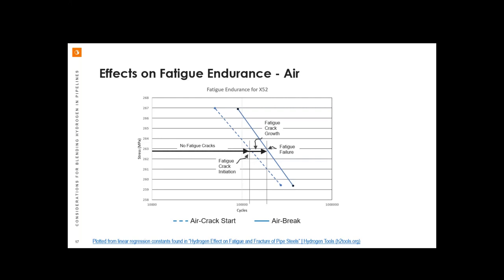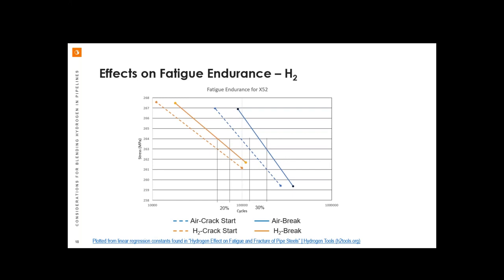And if it's left growing, it will eventually fail. And of course, in a pipeline scenario, we do have fatigue cracks that sometimes happen, and we need to monitor them and fix them before they become a problem. So this French paper, the reference is below. They're part of the European initiative, I think, NaturalHy. They're looking at pipeline blending in that part of the world. Unlike all the other data I'm showing you here, they're actually using hydrogen that was charged electrochemically. So that's a bit of a caveat because it may not truly represent what we see in our pipelines.